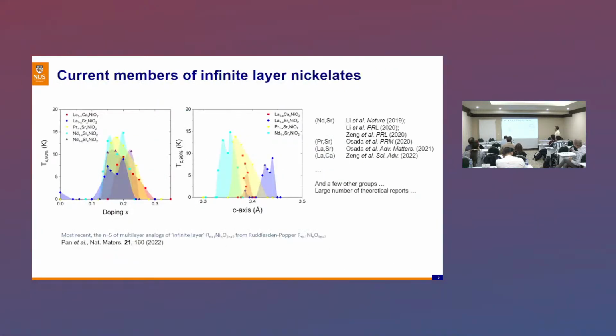Right, so more or less this is what we have obtained these days. These are different nickelate superconductors, Nd-based and lanthanum-based, with strontium or calcium doping. Also recently, based on the multilayer analogs of the infinite layer from the Ruddlesden-Popper compound, Mundy and his group have been able to produce superconductivity as well, even though the Tc is very, very low and doesn't reach zero resistivity. And of course, a couple of other groups have also been able to produce superconductivity in this nickel-based superconductor.